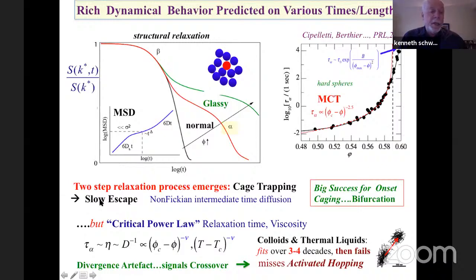The problem as I see it, and I think nobody probably disagrees, is that the time scale it predicts for relaxation obeys a critical power law. And so it actually predicts there's a divergence, which is typically far above the glass transition in the lab, or above the volume fraction in experiment.